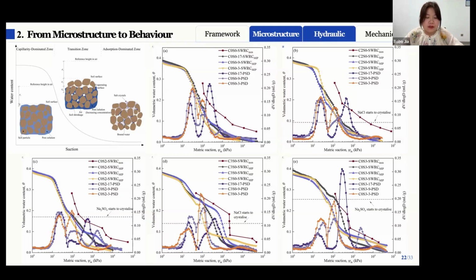Firstly, salt crystals tend to fill larger pores, reducing the pore connectivity and limiting further water migration. At the same time, the remaining solution is drawn into the smaller pores when crystallization continues, leading to the partial filling or blockage of micropores. And then for sodium sulfate in particular, crystallization is associated with significant volumetric expansion. When this occurs in confined pores, it can generate local stresses and induce microcracks, which further modify both the pore structure and the pathways of water migration.